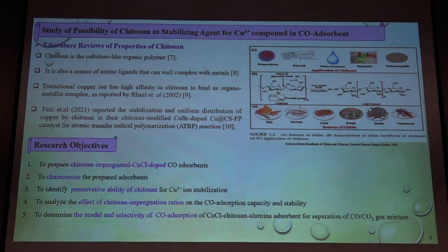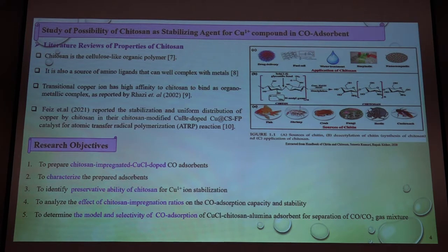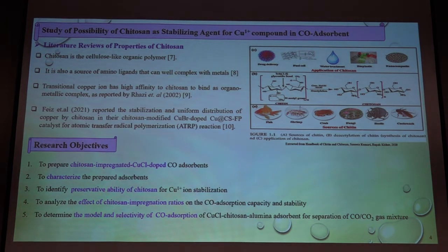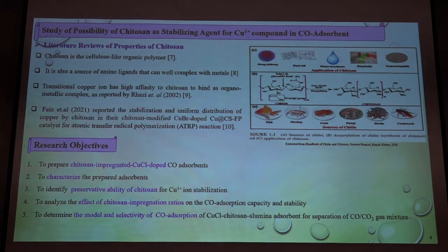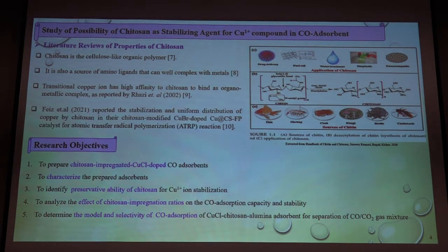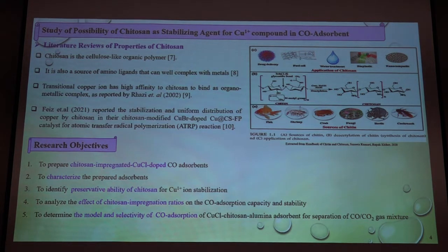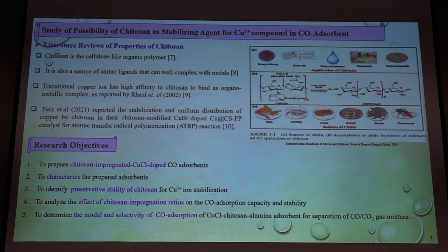On the other hand, one previous research reported that good dispersion of copper metal can be assisted by the addition of chitosan in the catalyst. So by this research review, I propose the chitosan-modified CO adsorbent with 30% CuCl doping. Firstly, I want to identify if the chitosan really has the preservation ability for CuCl to get a stable CO adsorption capacity even under atmospheric conditions. And afterward, I will analyze the effect of the chitosan addition amount on the stabilization proficiency of the CO adsorption capacity.